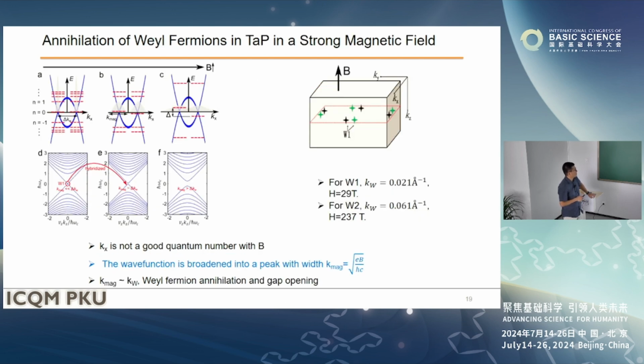Meaning, if you apply a very strong magnetic field along this compound, you have some opportunity for magnetic breakdown, meaning the electron wave function will overlap for these two Weyl pockets. At that point, because these two pockets have different parity, when the wave function overlaps, the only thing that happens is it will open a small gap. And with this gap open, we have a Weyl annihilation in a strong magnetic field.